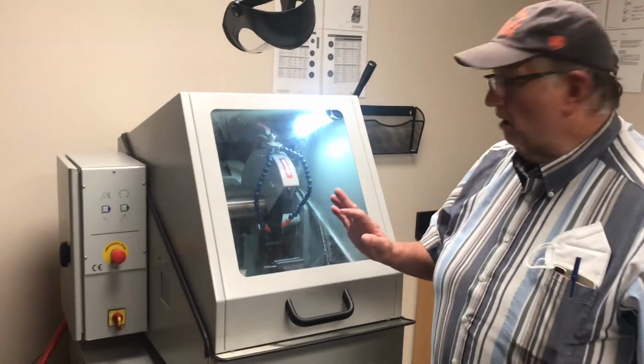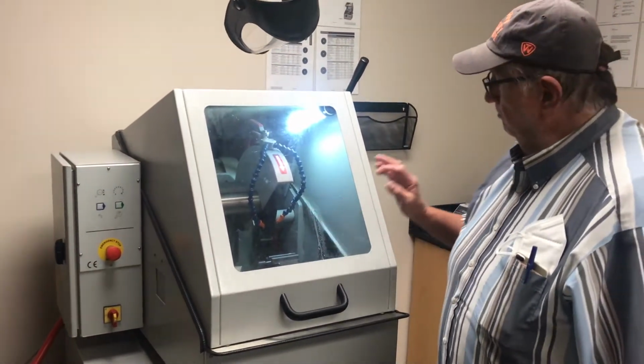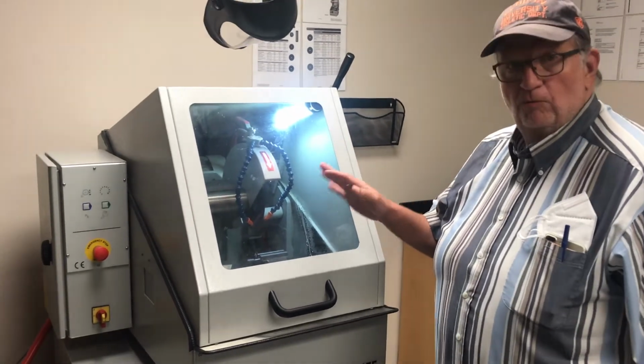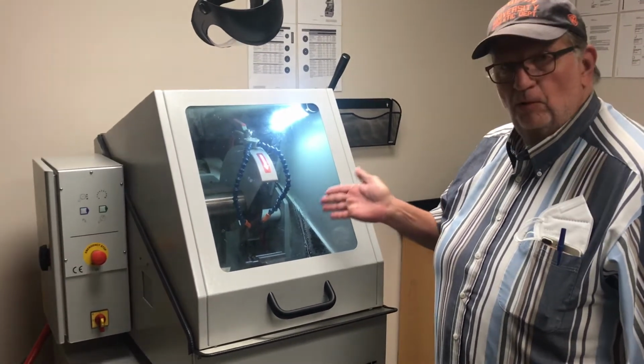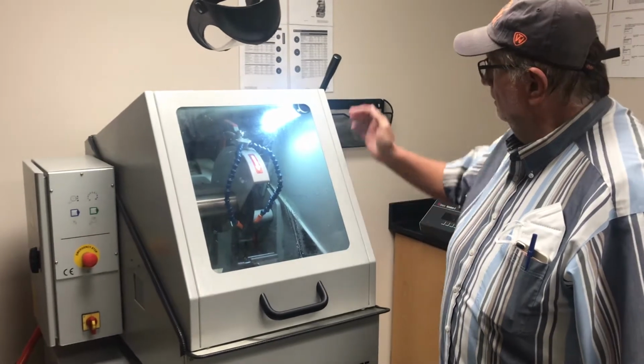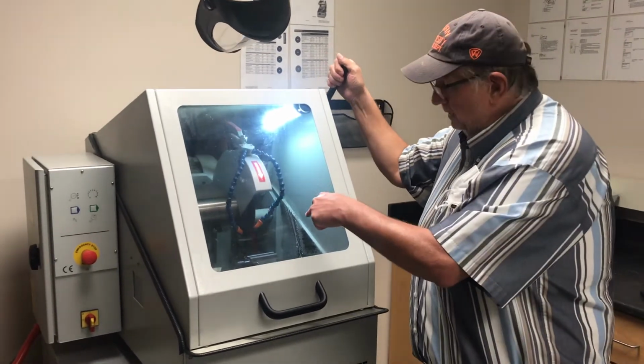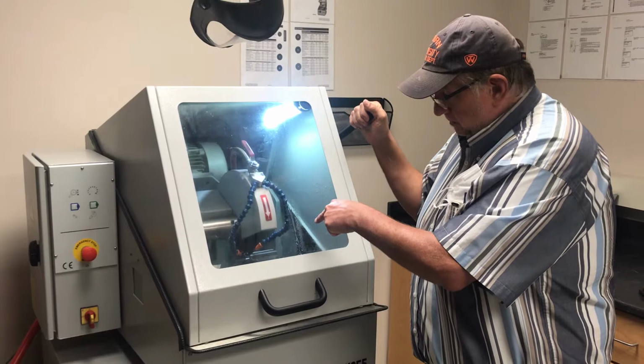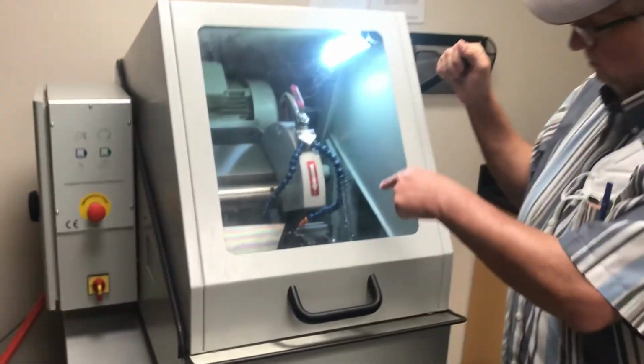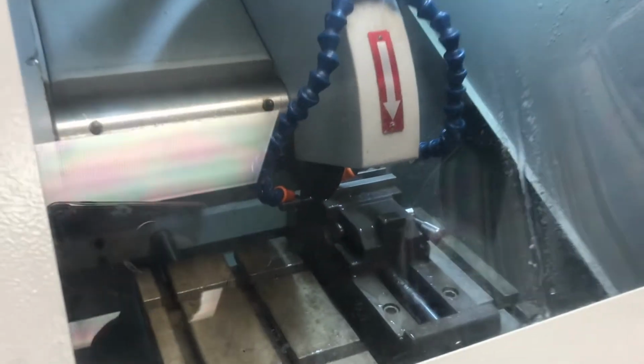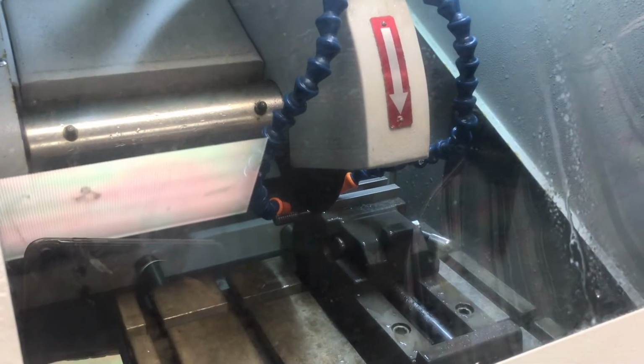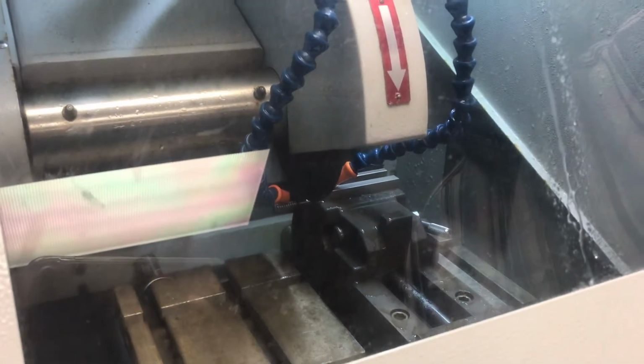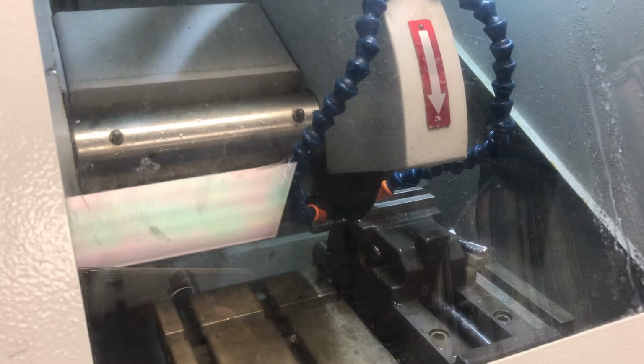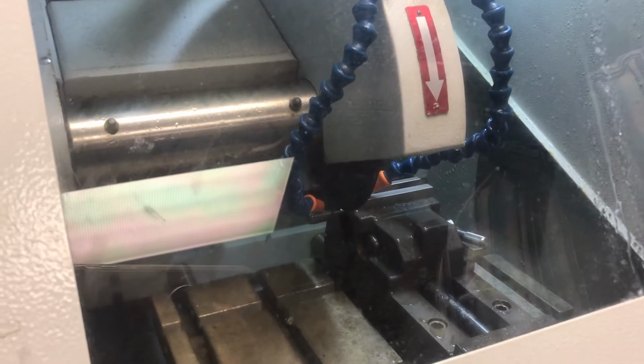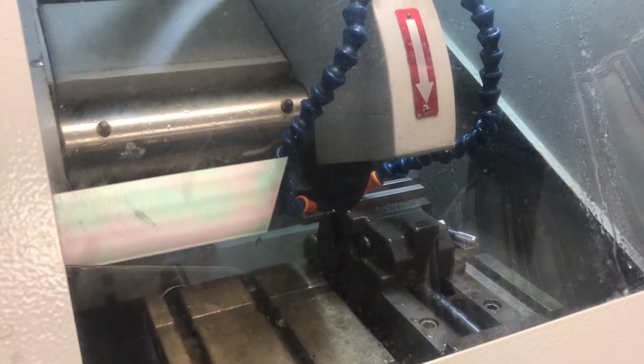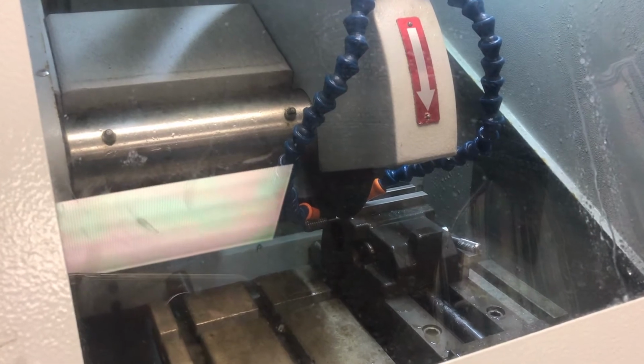I'm going to turn that off so you can hear me, but with the saw running and the lubricant running and pointing at the blade at the cutting action, gently pull the blade down, make contact with the sample, and cut the sample. Do not press or pull hard. You do not want to do this quickly. Take 1 or 2 minutes, gentle, firm pressure, and you'll see sparks. That's okay.